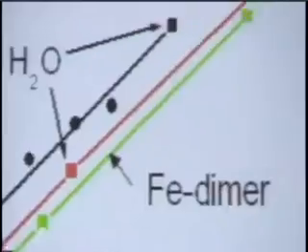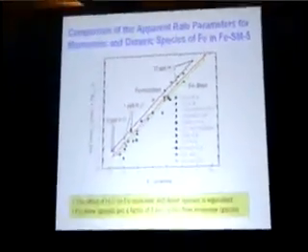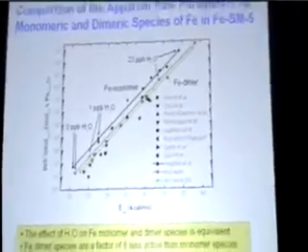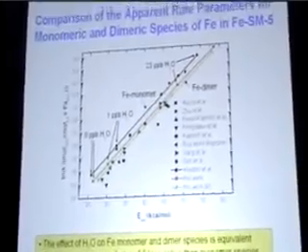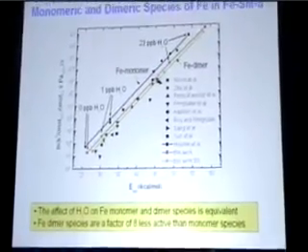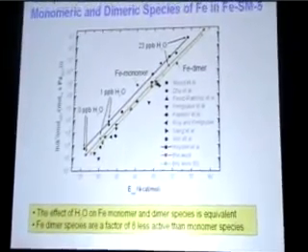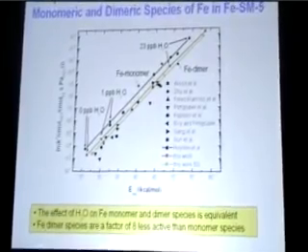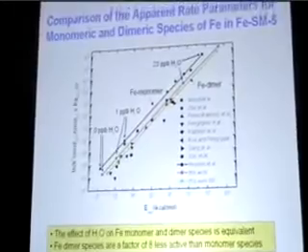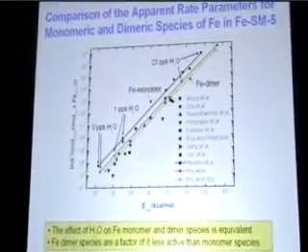And that accounts for the spread and certainly the angle over here, and suggests that what people have done unintentionally, because of the small amounts of water involved, is work with N2O streams having different amounts of water. It was an uncontrolled parameter. But once you recognize it, you capture that effect over here. And you see that the monomer is somewhat more active than the dimer. It's a factor of 8, not very large. But if you look at the difference between the black and the green line, it captures most of the data.